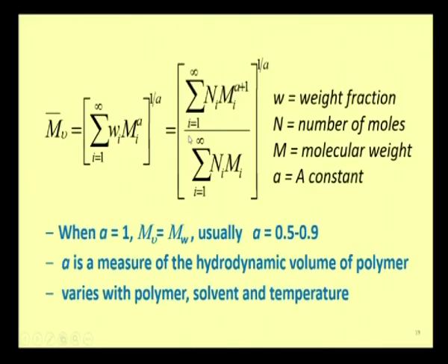The polymer is prepared in different concentrations, different viscosities of solutions are available, and the flow time required for the flow of such different concentrated or different viscous solutions is used for the calculation. Such molecular weight, whose calculation is based on the viscosity of the polymer solution, is called the viscosity average molecular weight.